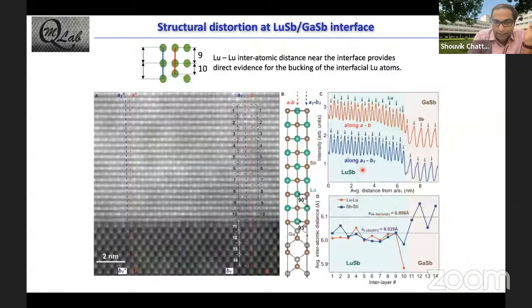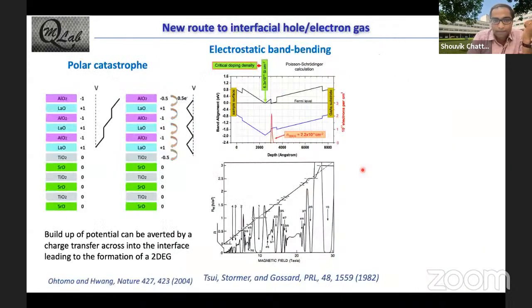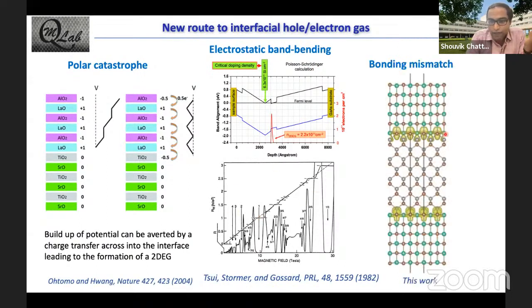So I think with this, this is just a little more detail. I won't go into this in the interest of time. What we think is that, in the previous talk, you had heard about this idea of polar catastrophe, where you slap together a polar and a non-polar material, and then you have this polar catastrophe induced 2-deg at the interface. Of course, we know that we can induce a 2-deg by electrostatic band bending, and this has been very successful in the realization of integer and fractional quantum Hall effect, which I'm showing here. But we think that we have now found another way of stabilizing a 2-deg at the interface, which is more by chemical means, due to the bonding mismatch.